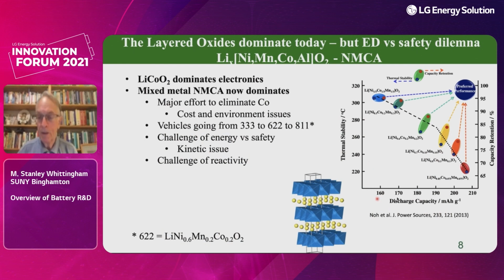And this is a famous plot now by the South Korean group of Yang-Kook Sun. And you can see if we want the highest capacity, we've got about 85% nickel. And this will release oxygen readily at 220 degrees centigrade. I should point out, this means these compounds are metastable even at room temperature. So given the opportunity, they will release oxygen there.